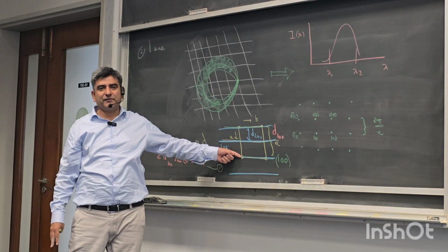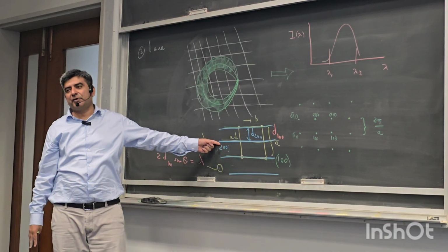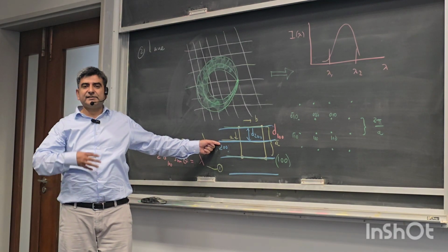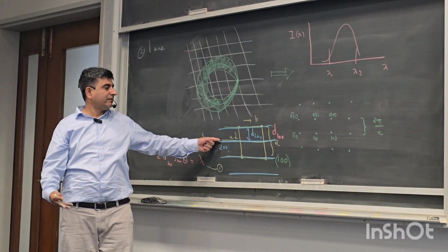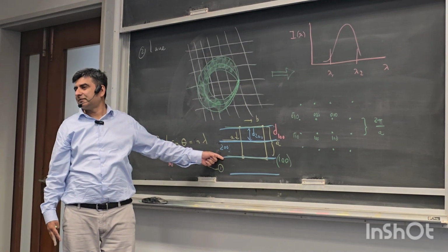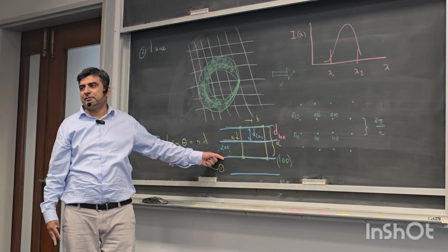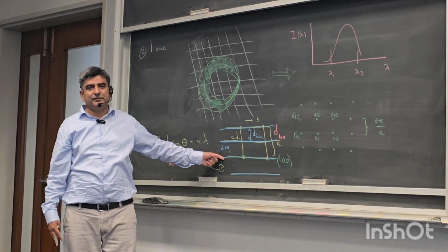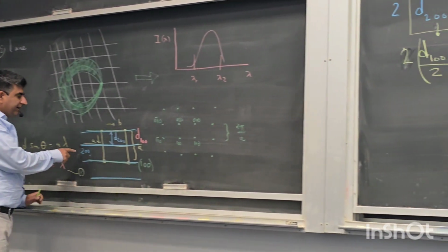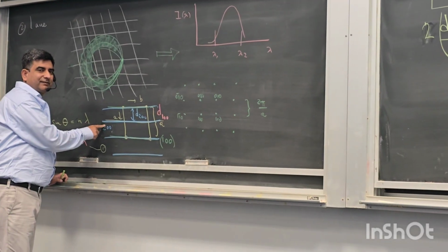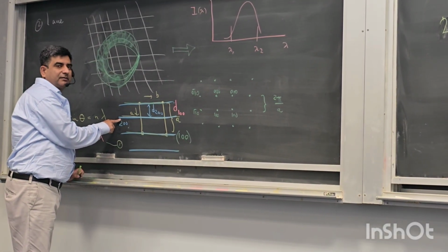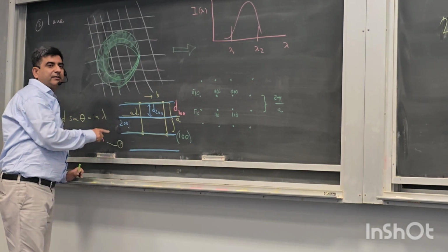So a first order reflection from this 2,0,0 reflecting plane is the same reflection as a second order reflection from the 1,0,0 planes. So it's unnecessary to include this reflecting plane.